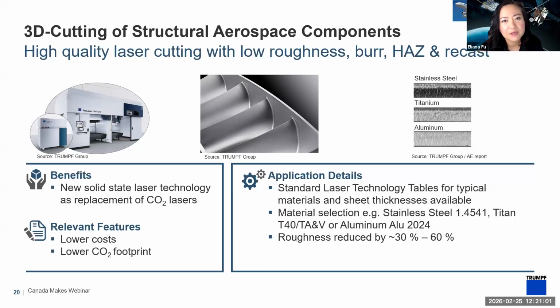at TRUMPF in Germany. This is comparing different typical materials, stainless steel, titanium, aluminium, and looking at how the precision of the cutting, basically measuring surface roughness, can be done. In a series of tests, we determined that the roughness can be reduced by 30 to 60% depending on the parameters that you use, featuring a TruLaser Cell. A TruLaser Cell is basically a laser contained within a safe box. Whenever you do laser processing, if you need to protect your eyes, you can build your own cell. If you don't have your own dedicated cell, you can buy a cell, which is basically a machine with laser safe doors that you can access, and the laser only turns on once the door is closed so that no one's eyes are going to be damaged. So we found that using this kind of setup, we can achieve these kinds of reductions in roughness.